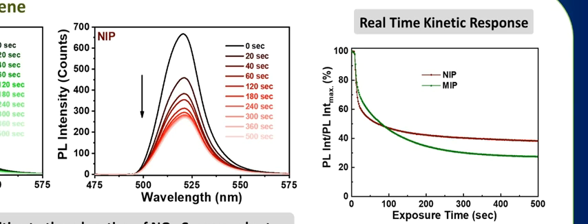The real-time kinetic response of cesium lead bromide polycaprolactone films to 3-nitrotoluene as a function of exposure time can be better observed in this figure by using the normalized PL intensity as a response variable. As we can observe, the NIP sensor is faster than the MIP sensor, but the MIP sensor is more sensitive. Furthermore, both sensors are capable of sensing this type of analytes because the PL intensity decays faster within the first 20–30 seconds, and after 50–60 seconds the sensor is saturated with analyte and the PL intensity decreases much more slowly.